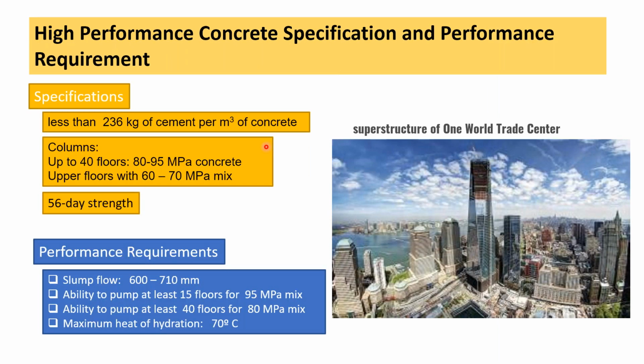I'll just give you an example of a high performance concrete specification. If you look at the concrete that was placed in One World Trade Center, specifications were put in place. The cement usage in concrete was specified to be less than 236 kilograms per cubic meter of concrete. This was for concrete that was expected to achieve compressive strengths of about 90 megapascal in the first 40 floors, and a compressive strength in the range of 65 megapascal for the higher floors. So the expectation was that these high strengths could be delivered using a very small amount of cement.